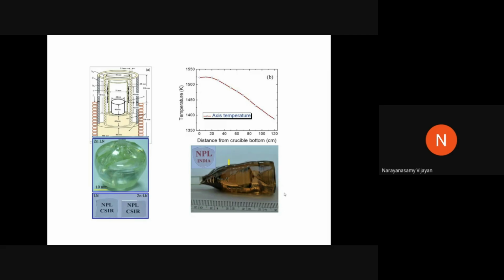In the Czochralski technique, we used an RF furnace, a radio frequency furnace, and above that we made a small resistive heating element, because after the growth we have to keep the crystal for some time to come to room temperature slowly, because the melting temperature is approximately 1233 degrees centigrade.